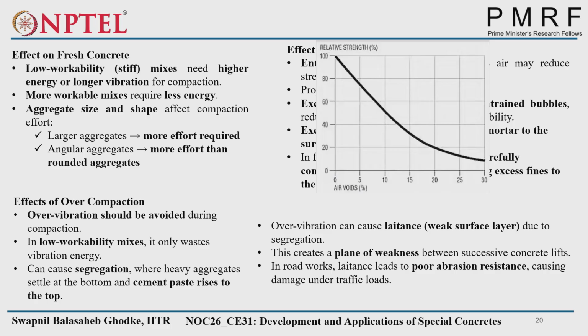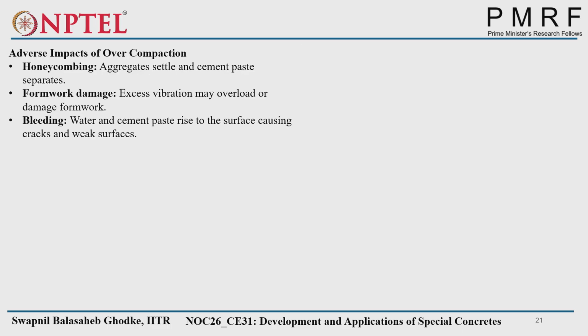Suppose you are doing a column, you cannot place it in one lift. For a large height column, you are pouring in continuous lifts. At that time you are doing a higher amount of compaction for the lower part. So what happens, the cement particles will come to the surface, that will create laitance, a weak surface layer. And when we place another lift of concrete over that one, a cold bond will be formed, that is the weak bond between the two surfaces. So that should not be there. That's why we sometimes remove that weak surface also.